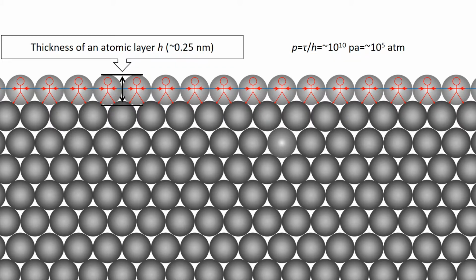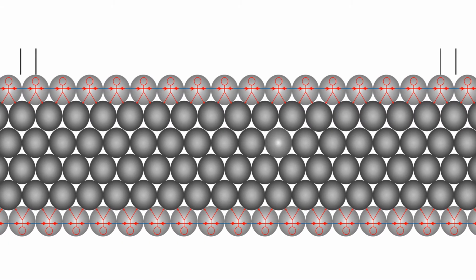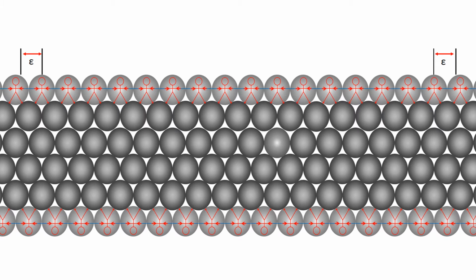As the thickness of an atomic layer is about 0.25 nanometer, or 2.5 times 10 to the minus 10 meter, this surface stress can induce a surface pressure on the order of 10^10 Pascal, or 10^5 atmospheric pressure. This huge pressure provides a strong driving force for the compression of the lattice to reduce the surface energy. While this surface pressure has little effect on metals with macroscopic thickness, it can lead to generation of strain on 2-dimensional nanosheets, as nanosheets are analogous to springs.